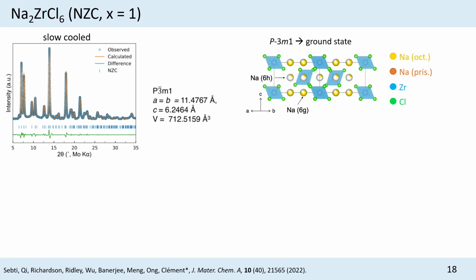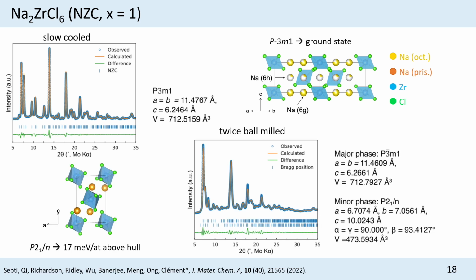So clearly here, we have a good handle on phase purity. It's also the ground state structure that we find with DFT, so this makes sense. We're making it under thermodynamic conditions. Now if we quench it and ball mill it again, so this is the twice ball milled sample, we now start to have a mixture of phases where our major phase is still the ground state, but now we're forming a minor phase that has the same space group as the other end member, the yttrium end member, so the monoclinic structure here. This structure is 17 meV per atom above the hull.